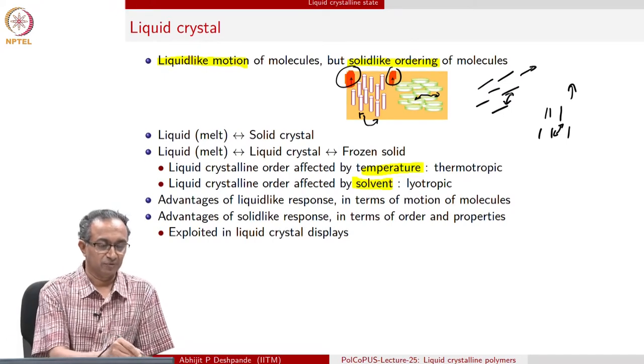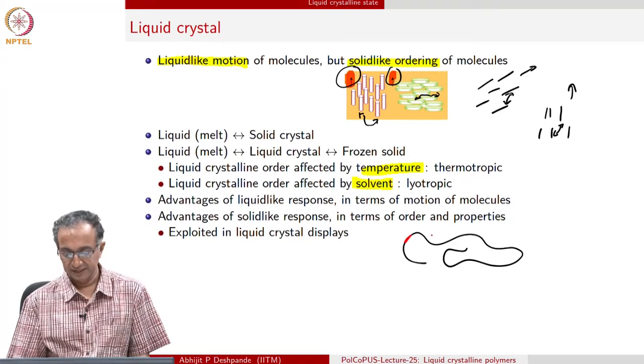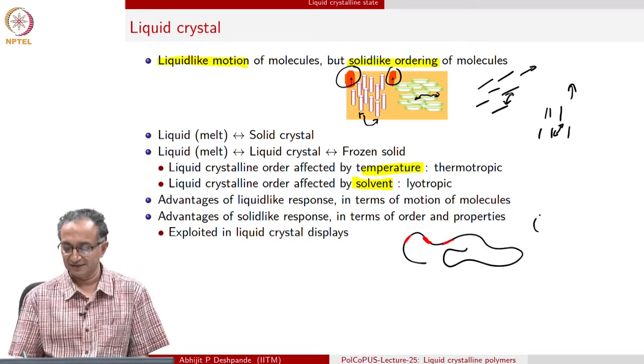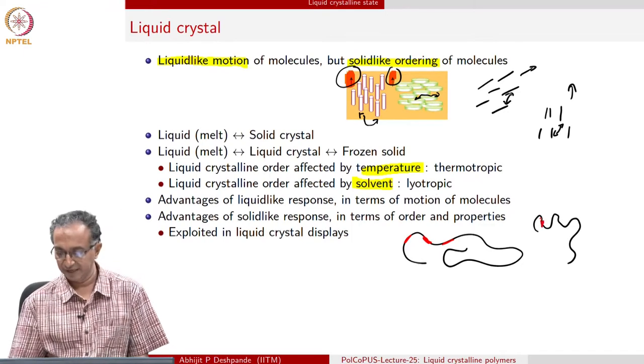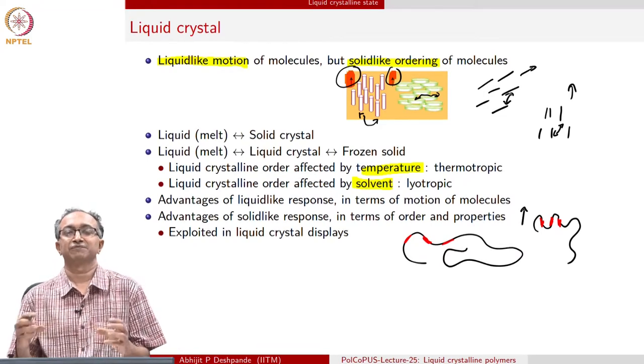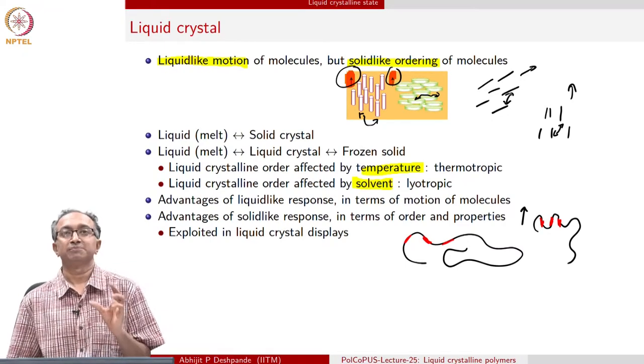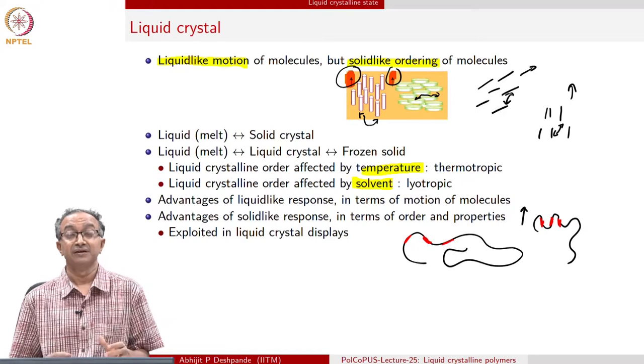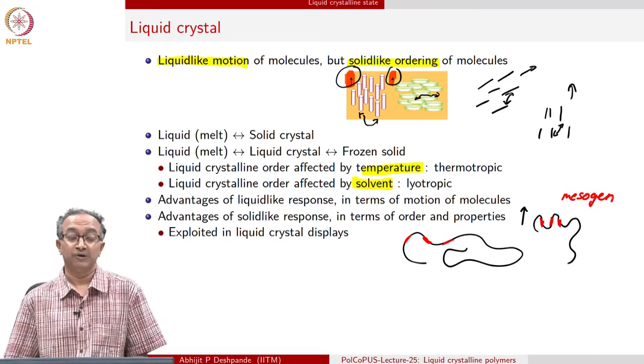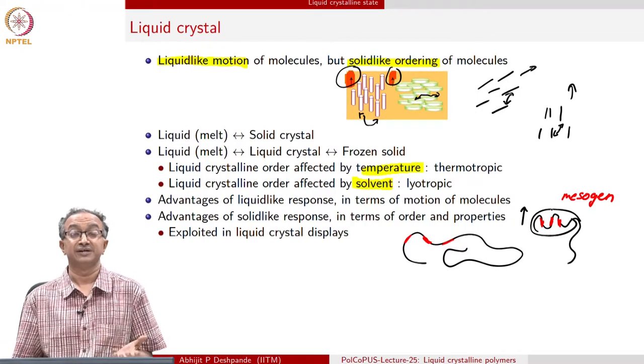Now, given that we are looking at a macromolecule in this course, what we are looking at is those sets of macromolecules where in parts there are rigid rod-like moieties. What can happen once you have this kind of system is that some amount of ordering can take place between these rigid entities. Just the way we drew a director vector for a small molecule liquid crystal, these segments of a polymer chain can align themselves and therefore we can again look at a director vector. These small groups which prevent bond rotation or which lead to the chain being rigid locally are called mesogens. Depending on what kind of macromolecule we have, we could have mesogens along the backbone, or as a branching point, or as a side chain.